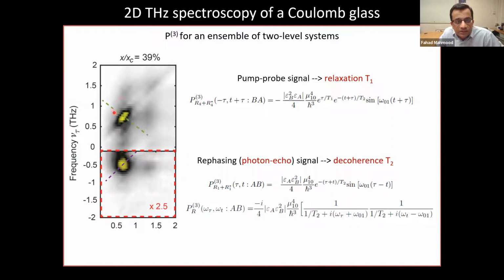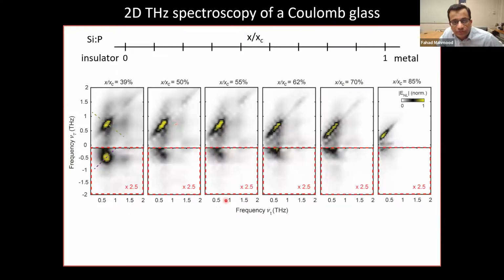This signal here is what's known as our pump probe signal. So this is your classic pump probe spectroscopy measurement where you send in one pump pulse and then see how the system relaxes over some time. Okay? The width of that gives you that pump probe time, or the energy relaxation T1, okay? So we can do this as a function of doping. I should point out here that we're doing this on the insulating side of phosphorus doped silicon. So this is expressed as a function of the critical doping. So 100% would be the metal insulator transition.